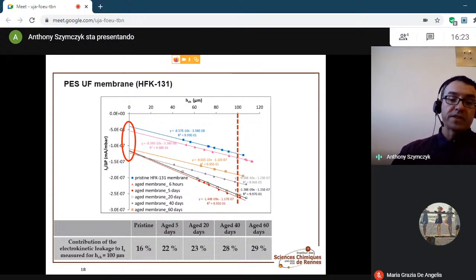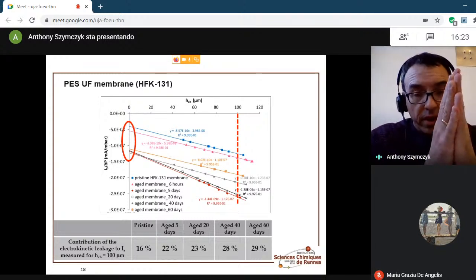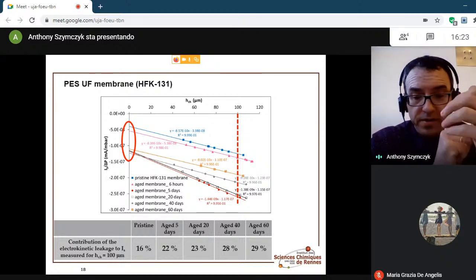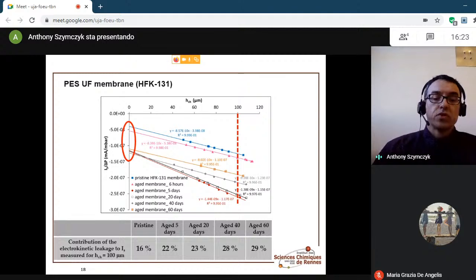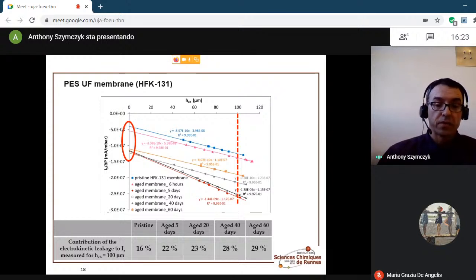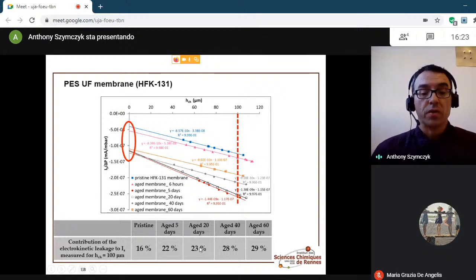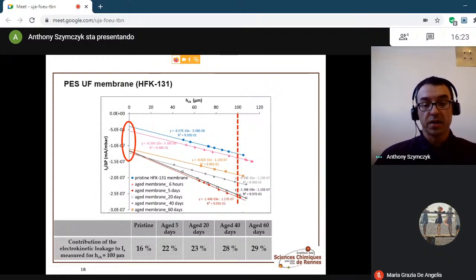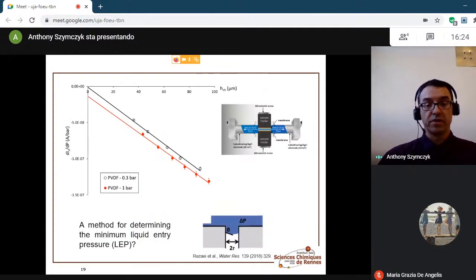On the contrary, when the same type of experiments are carried out with an ultrafiltration membrane, also in PES, an increase in the contribution of the electrokinetic leakage to the measured signal is observed as the time of exposure to chlorine increases. This suggests that the internal structure of the ultrafiltration membrane is impacted by aging, but not that of the nanofiltration membrane. It is also noted that the contribution of the electrokinetic leakage for the pristine membranes is greater for the ultrafiltration membrane than for the nanofiltration membrane, which is explained very simply by the greater porosity of the ultrafiltration membrane compared with the nanofiltration membrane.